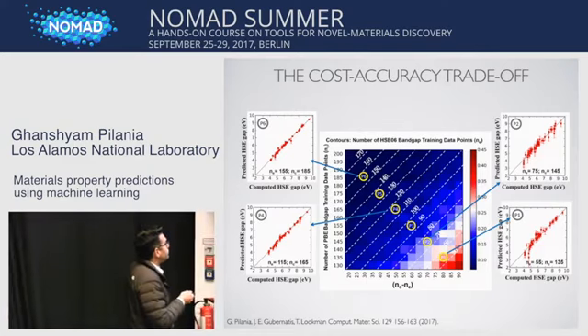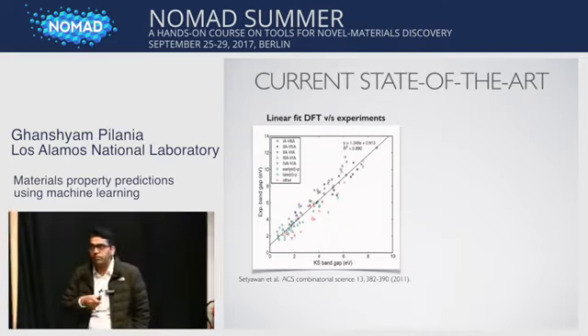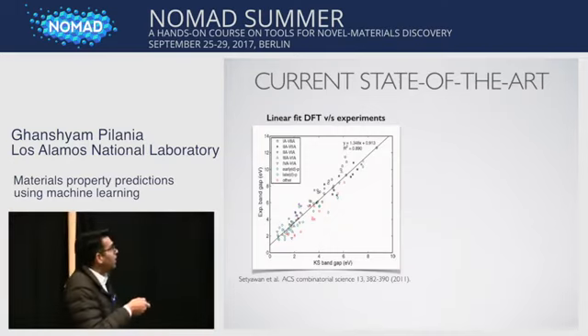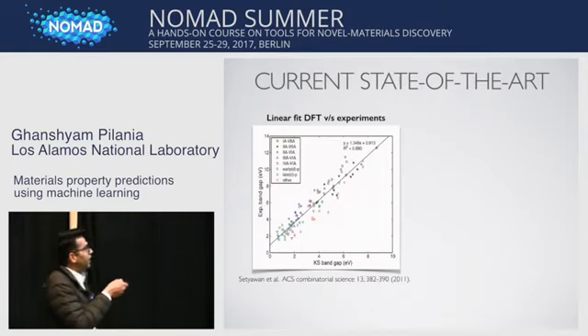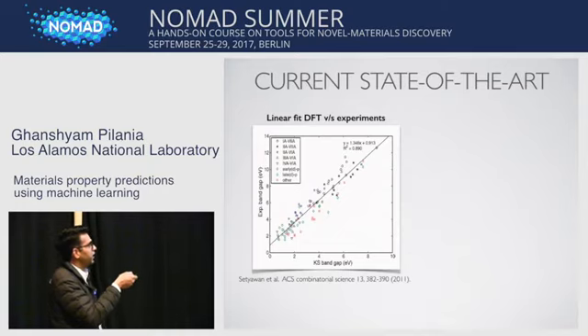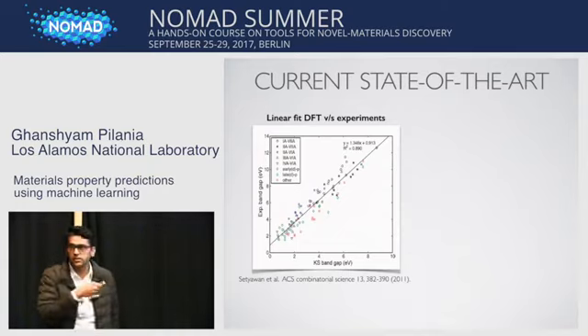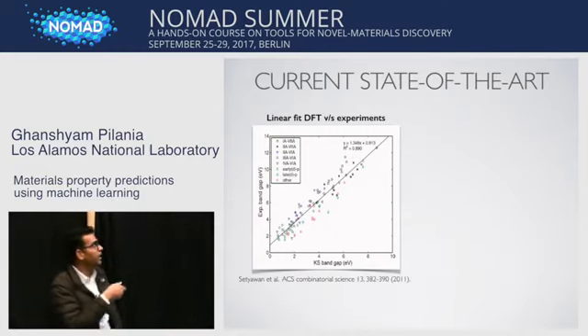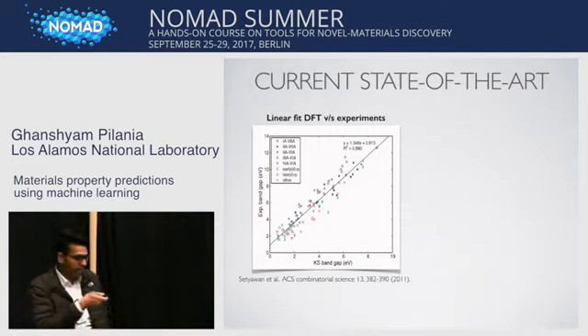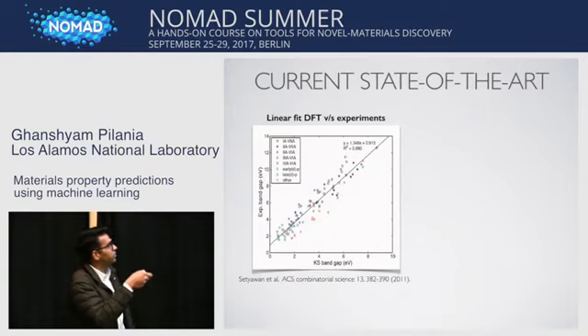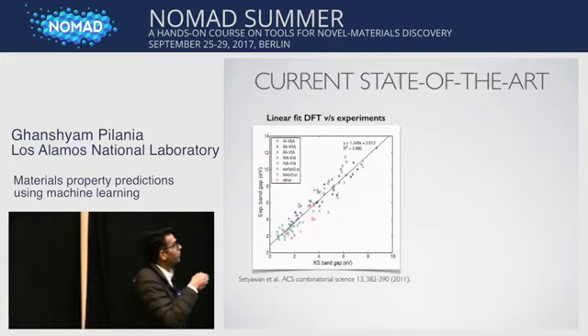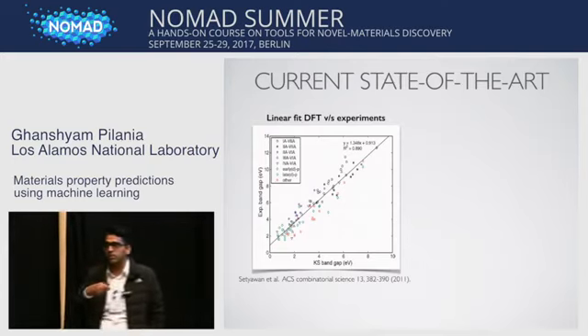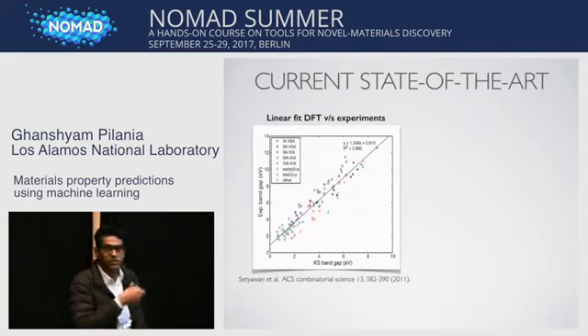So let's compare it with state of the art. It's a general practice to actually fit such straight lines. So on x-axis we have our, let's say, low fidelity model, and y-axis, in this case it's an experimental data, but it could as well be HSE band gaps or GW band gaps. And in many cases it's possible to fit a straight line, and this is very efficient. But if you fit a straight line, then you usually get much larger scatter. So the predictions you are going to be making will not be very good.